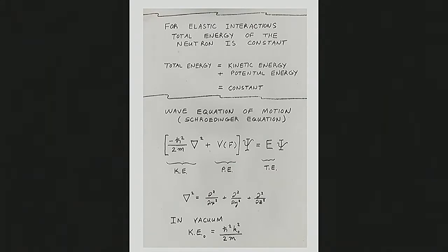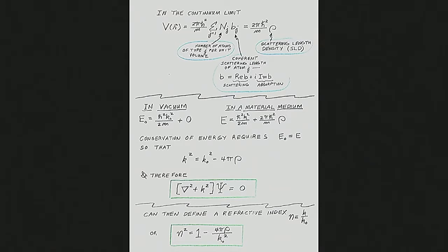Quantum mechanically, analyzing the wave function that represents how the neutron or photon interacts with the material is just conservation of energy — kinetic energy plus potential energy must equal total energy at all times and places. For neutron scattering at low Q, the potential looks like a number density multiplied, for each constituent atom, by a corresponding scattering length. For nickel it's one number, for iron it's another, for hydrogen, for carbon — different numbers. Multiplying by density and the proper constants gives a scattering length density.